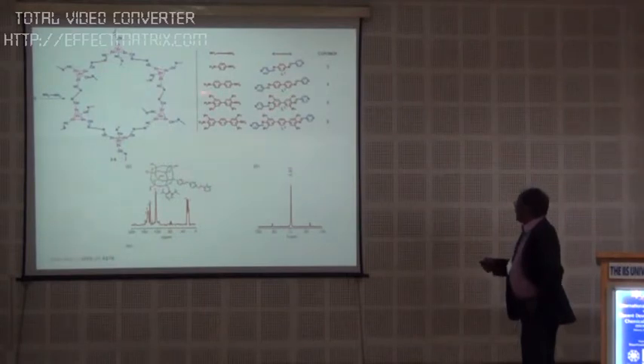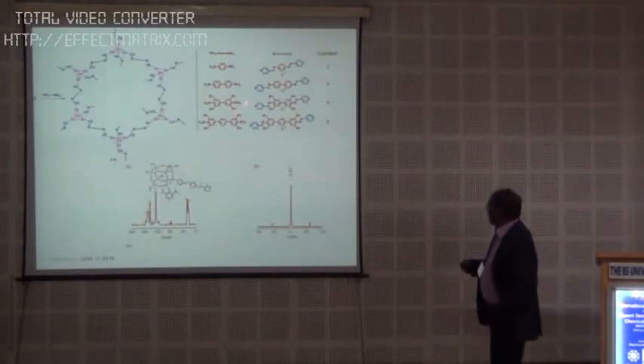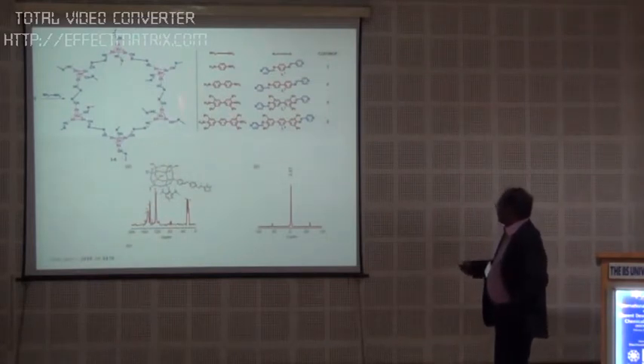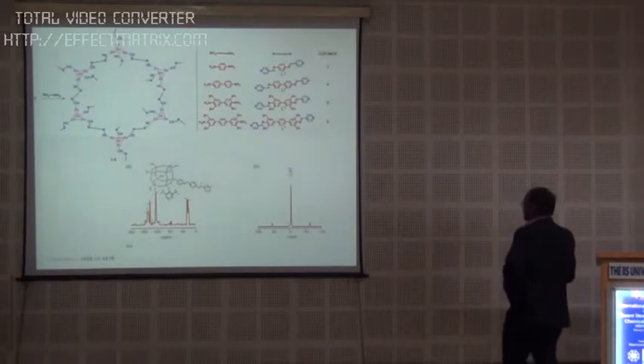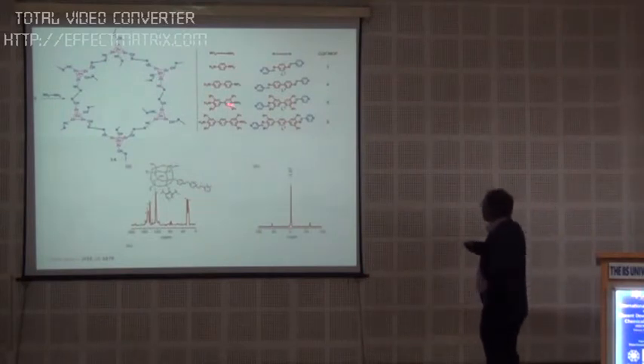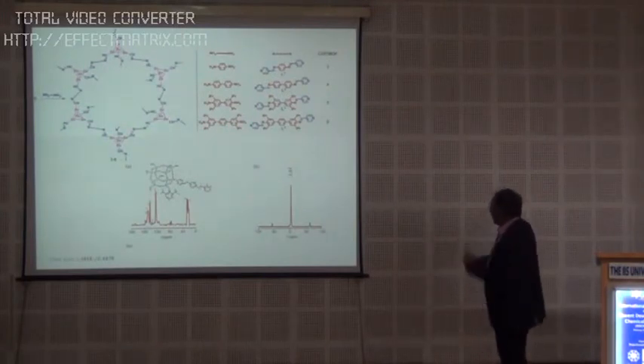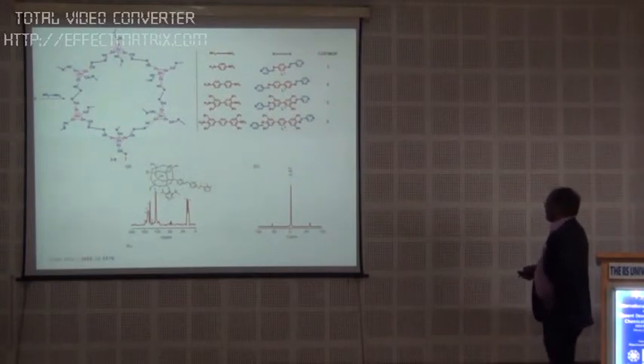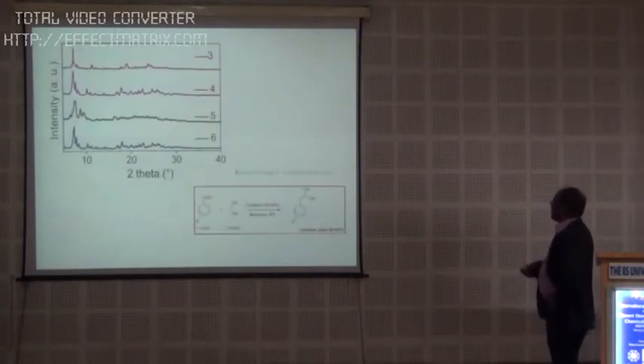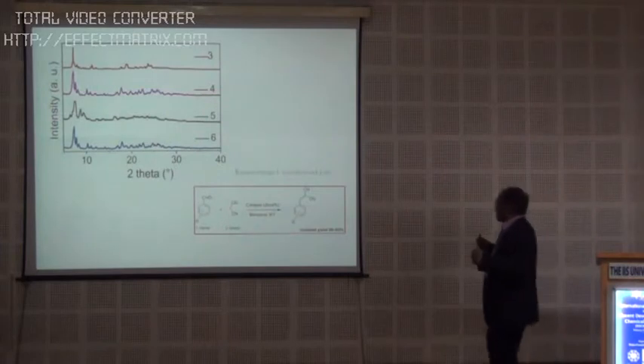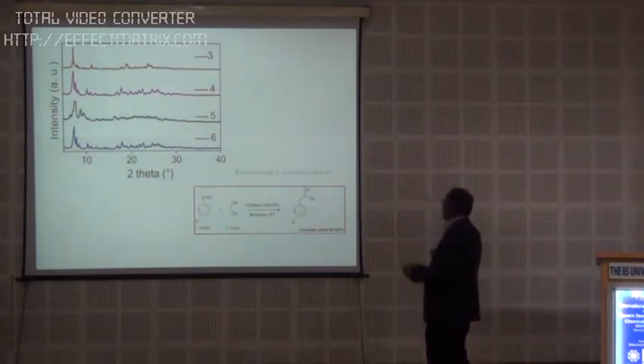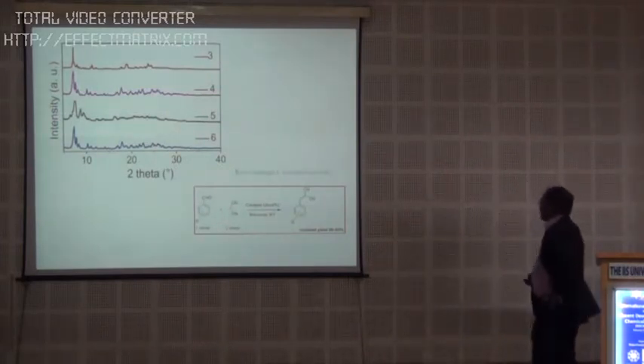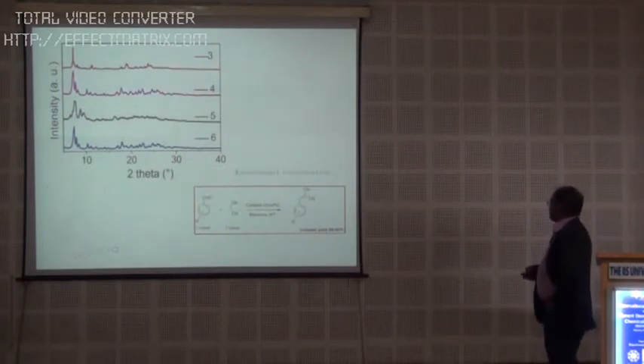And when we introduced isopropyl groups, again the same strategy as what was spoken about, you can actually start growing single crystals. Often these materials are amorphous, you don't see too much crystallinity. But when you load this benzene with the isopropyl group such as this, and expand, you pull this out a little bit more, you can actually crystallize these compounds 5 and 6. I'll show you only one example, again to show that these are isostructural, only differing from each other by the distance between the 2 cubanes. Okay, and you can use them for a variety of organic reactions. I just showed one example here.